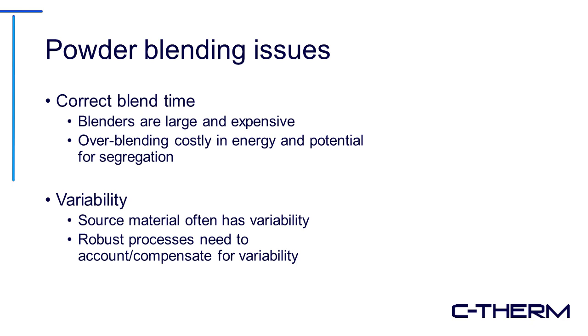Variability in the source material is often a major cause of process issues in these sorts of things. So if you have a source material that, for example, you're getting your iron from recycled iron, you're going to have a lot of variability in terms of the quality of the iron coming into your process, and that's going to lead to variability in terms of what's coming out of your process. So what you can do is, if you understand the blend well enough, you can design a process that will compensate for starting material variability so that even if your starting material is variable, you get a consistent end product coming out the other side.